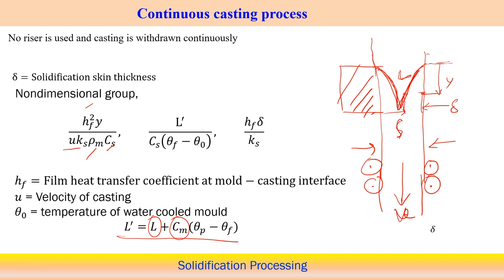So here you can find L prime, and Cs is the specific heat, and then theta f minus theta 0. So theta f minus theta 0 is another non-dimensional parameter, and we can use these non-dimensional parameters to calculate the other parameters, in terms of the film heat transfer coefficient hf, delta at a distance y, and Ks. Ks is the thermal conductivity of the liquid metal.